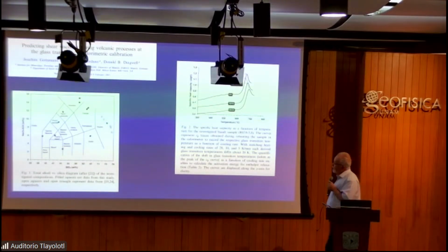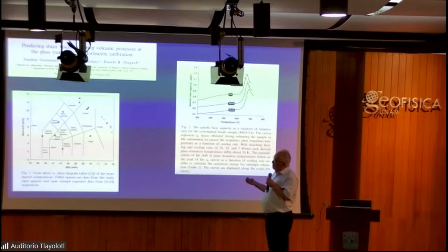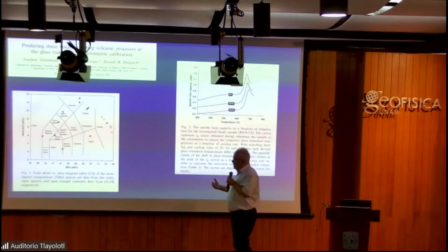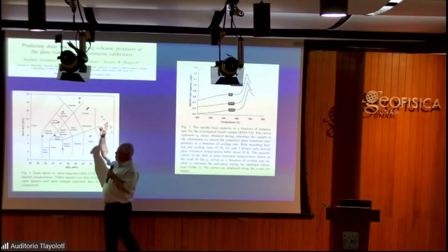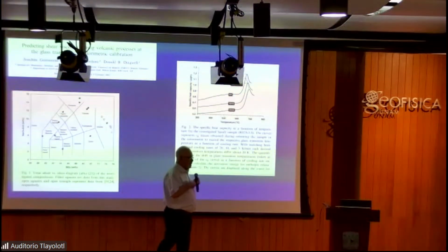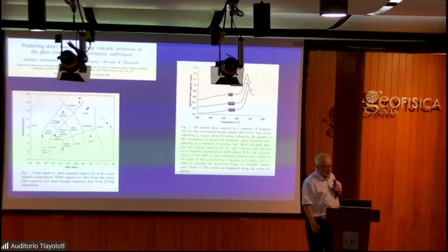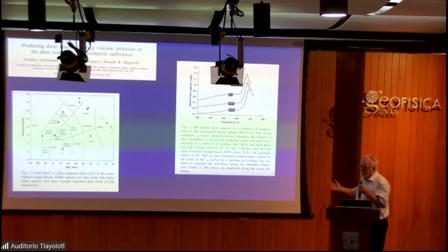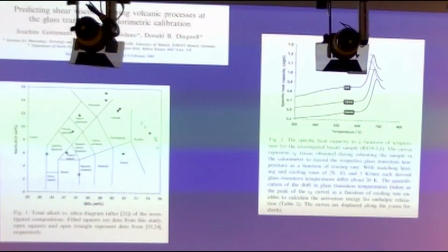So, I have to take you through a couple of methods that we developed to help you to understand what I say next. We've taken glasses from this entire range of composition of natural materials, terrestrial natural glasses. There will be other ones on the other planets, of course. We already know from the moon. And then what we do is we heat them up and we measure their heat capacity in a calorimeter. And if you take a glass and you heat it up, and if it does not crystallize, then it will give you this. This peak is what we call the glass transition. It's the enthalpic expression of that golden or yellow curve that I showed you earlier, okay?